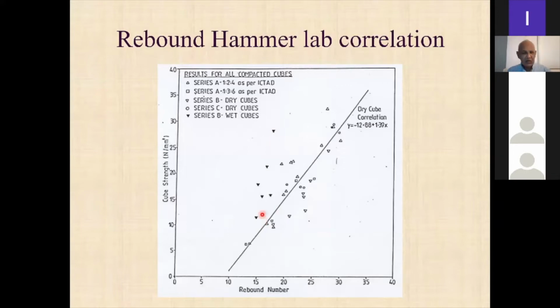So the story from this that I want to say is, if ever you are taking rebound hammer readings, you have to ensure that the surface is dry. If it is a wet surface, then the rebound number will only be a reflection of that wet surface, the hardness of which will be reduced because of the moisture.